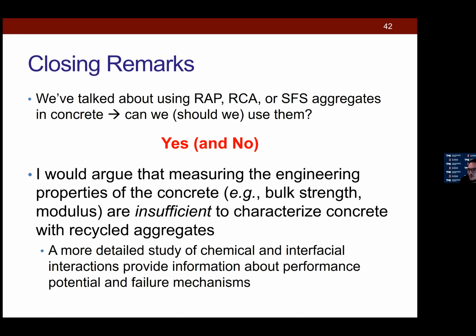Yeah, well, in the lab, I'm using some aggregates that are close to dry, some other half of SSD. And since I'm measuring properties in the first 30 minutes after batching, I'm usually excluding that absorption. So I don't over design in water to account for that water absorption. Yeah, well, RCC is kind of a different animal, so I'd probably agree with your methodology there. You can't exactly measure a slump, so are you somehow measuring workability or some sort of flowability? Compactability with the gyratory.